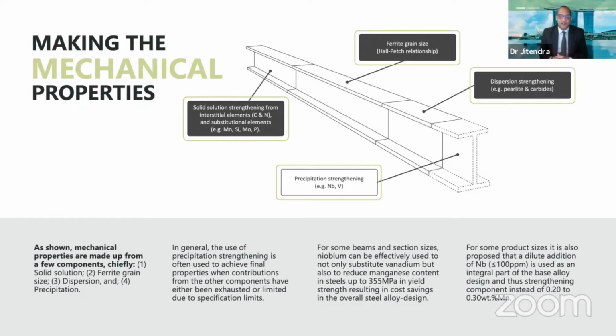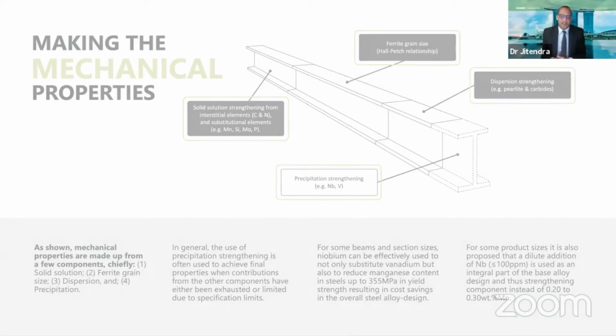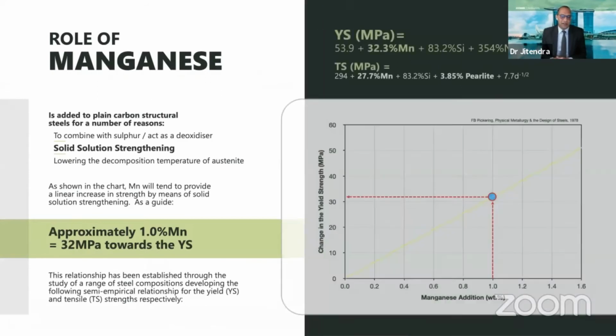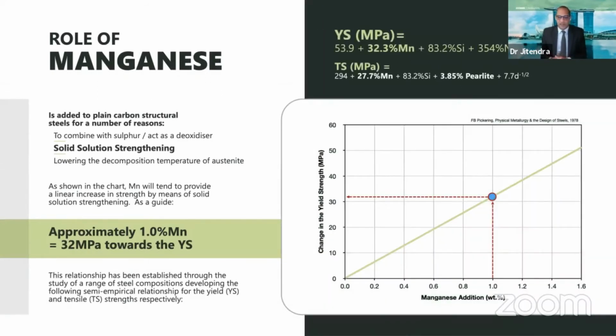But in these commodity grade steels, it's important to stress that the precipitation strengthening part is considered quite low in its strengthening contribution, because we're adding very low levels in here, particularly in the case of niobium. So these are the four major building blocks that we rely on to give us the target strengths that we're targeting. Now, this graph shows the solid solution strengthening contribution of manganese, which we are all accustomed to.